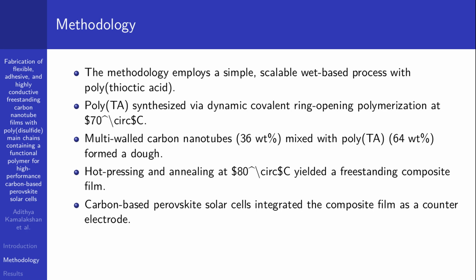Our methodology centers on a simple, scalable weight-based process utilizing a novel functional polymer, polythioctic acid or poly-TA. First, poly-TA was synthesized via dynamic covalent ring opening polymerization of thioctic acid, achieved by heating the precursor in chlorobenzene at 70 degrees Celsius. Next, multi-walled carbon nanotubes at 36 weight% were thoroughly ground with 64 weight% of the prepared poly-TA in a minimal amount of chlorobenzene, forming a dough-like mixture. This dough was then hot pressed and spread onto a glass substrate, followed by peeling and overnight annealing at 80 degrees Celsius, yielding a freestanding composite film.